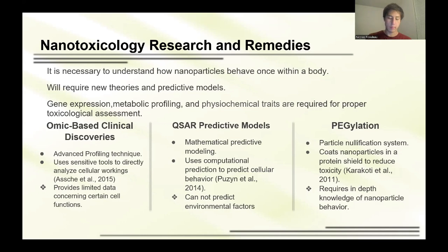In another experiment, PEG-coated gold nanoparticles showed less toxic outcomes than uncoated gold nanoparticles within 2 populations of Sprague Dawley rats. One population of these test rats was given nanoparticle contamination, and the other, the experimental population, was given nanoparticle contamination along with a PEG therapy, and it was determined that the treatment population showed less signs of toxicity than the control population. This may mean that gold nanoparticles may actually be safe for biomedical application and usage in various fields of biomedicine and do not risk harming the biological systems they're treating.